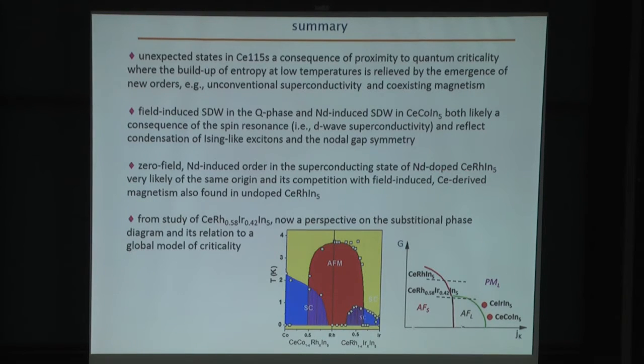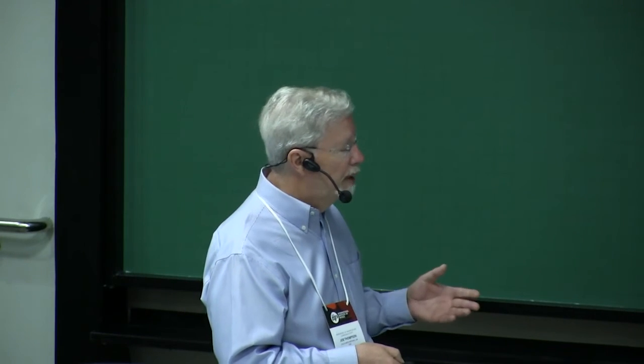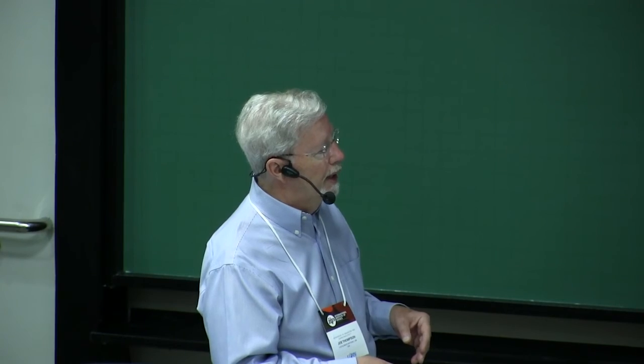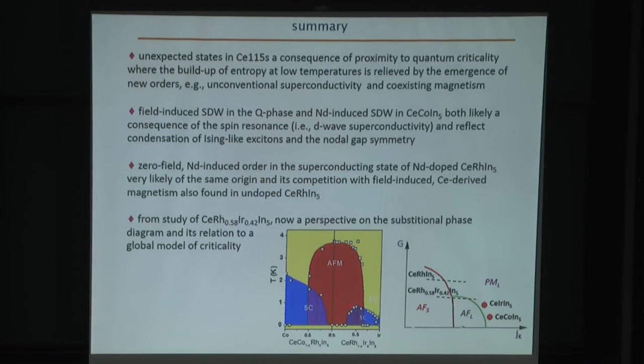In the case of cerium rhodium indium 5, we've seen that again, neodymium replacing cerium induces a zero field magnetic order, probably having the same origin as the spin density wave order in cerium cobalt indium 5, and that this zero field spin density wave order competes with the cerium-derived field-induced magnetism in the superconducting state of cerium rhodium indium 5. And then from the study of the iridium substituted material and what else has already been known about the cerium 115s, I think we now are able to provide a broader perspective on the substitutional phase diagram and the relationship between superconductivity and quantum criticality that underlies this superconducting phase diagram.